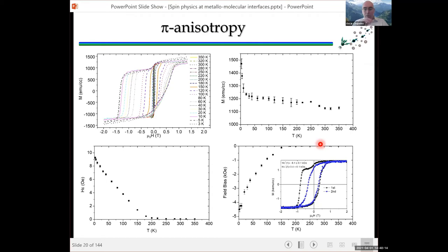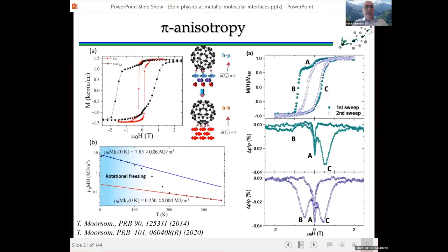So what we analyze with our collaborators in micromagnetics and DFT simulations is the charge transfer and hybridization at the interface between the metal and the molecule. And what we saw is that what is happening is we are forming a spin polarized electrical dipole that then pins the molecule physically in a certain configuration. And then you need a very large magnetic field to force the molecule to rotate. Once the molecule rotates in that magnetic field, then you destroy the pinning.